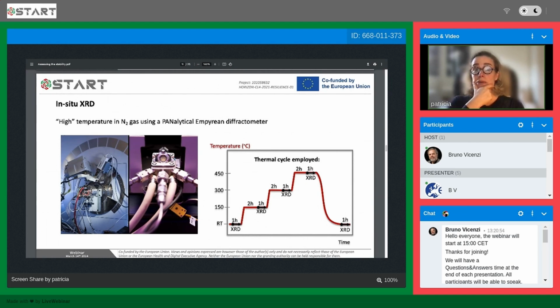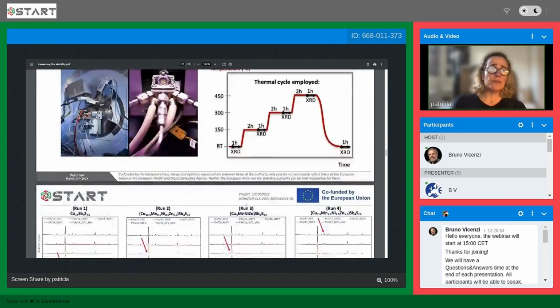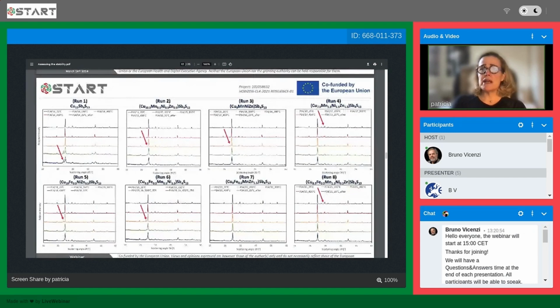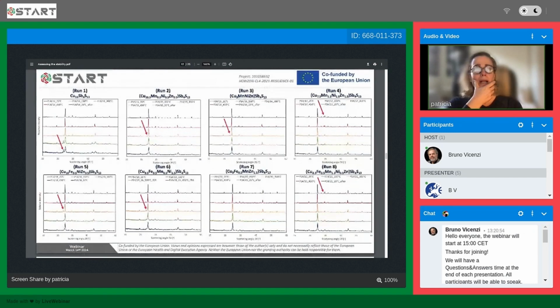Given that we are thinking of using tetrahedrite for temperatures in the range between 300 and 400, this was the thermal cycle that we have employed. And then if you look here, these are some of the runs we've done with these materials, which were a bit wild because they had too many substitutions. You can see the diffraction patterns acquired at different temperatures: the bottom one is at room temperature, and then the next one is 150, then 300, then 450, and then again, after cooling down, 25 degrees.